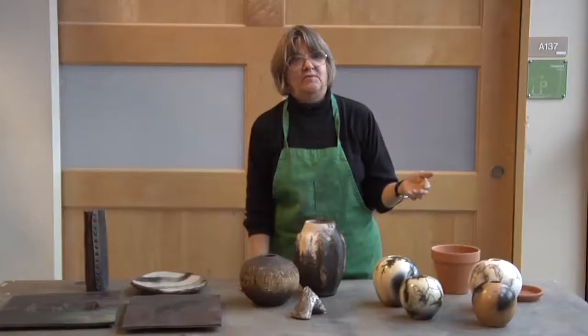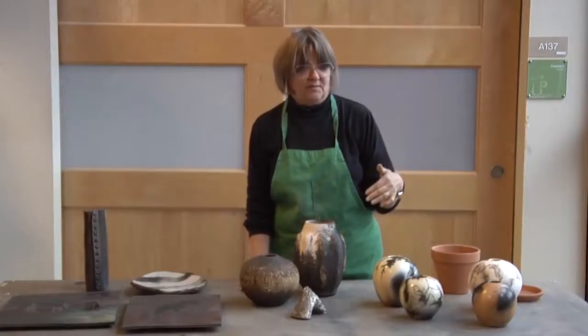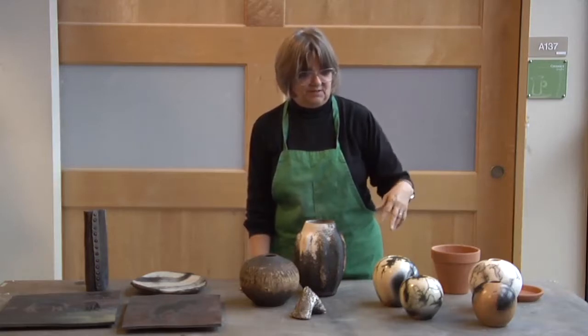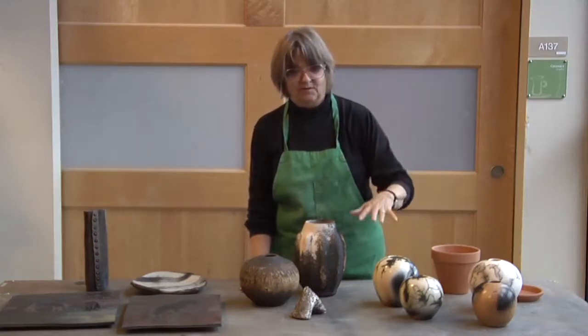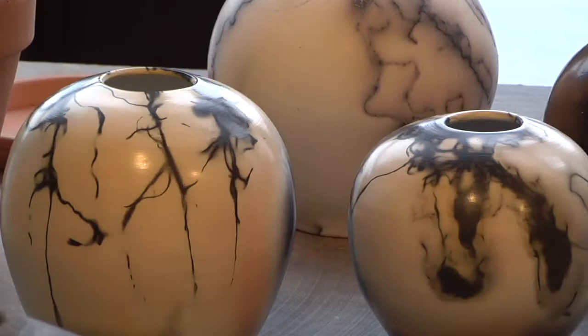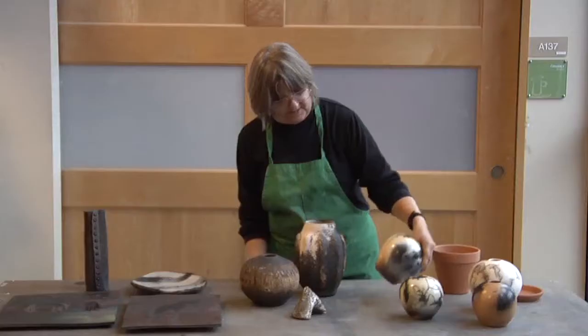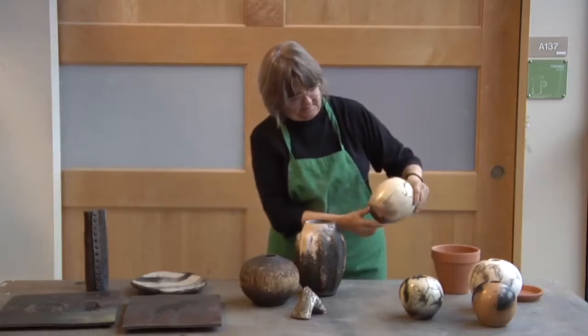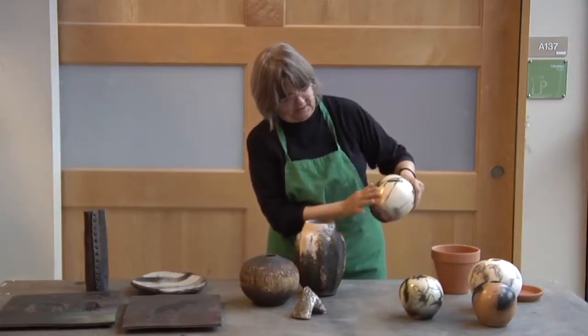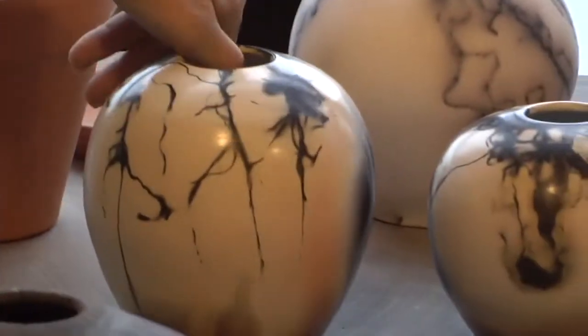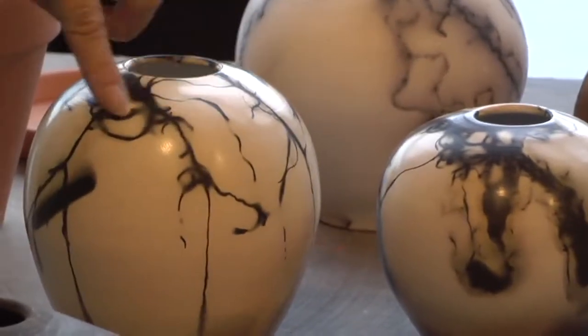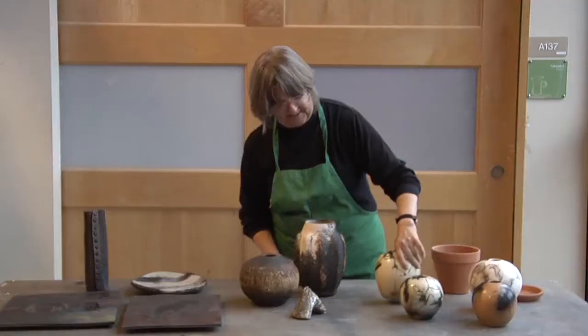I use a 3-part salt to 1 part copper carbonate stirred up and then mixed in with some sawdust, and that goes on a bed of wood chips and sawdust, so that it burns it up. And it gets some nice flashing from the fire in the bottom of the saggar. So this is from the copper, and this is from the copper wire, and there's a little bit of green in there.